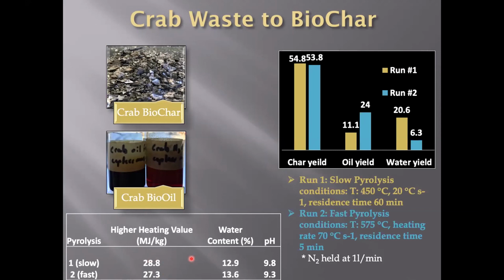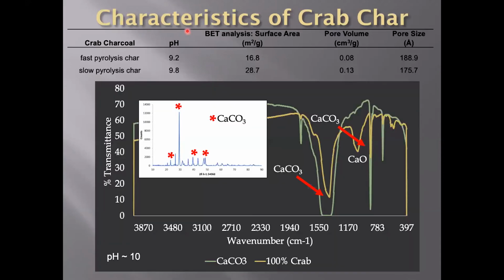We think it's probably because it has a fairly low water content and a high pH compared to forestry residue bio-oils that are typically acidic and have a much higher water content. We are now working on identifying the chemical composition of the crab bio-oil and looking into that more thoroughly. But as I mentioned, our main focus has been the crab biochar because it's the most high yielding product of the pyrolysis. And we wanted to get a really good handle on what the crab biochar was composed of. So we've done a really thorough characterization of this material.